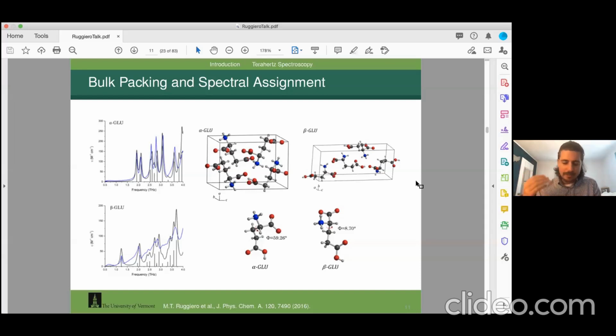If you remember, if you dig really deep to when you took maybe organic chemistry when you were in school, and you had to memorize those tables of all the transitions, okay? OH bond, 3400, carbonyl, 1600, CH stretch, 3000, et cetera, et cetera. So you can use FTIR as a method to determine, okay, I have an alcohol, I have a carboxyl, I have a carboxylic acid. You cannot do that in the terahertz range. So no matter how great I am, no matter how many awards I win for terahertz, if you gave me a terahertz spectrum of an unknown sample and said, Mike, what is this? I can't tell you. I would have no way of being able to interpret that, because each of these peaks is totally unique to the unique packing that exists in that one structure. And so one of terahertz spectroscopy's greatest strengths is also one of its greatest weaknesses.